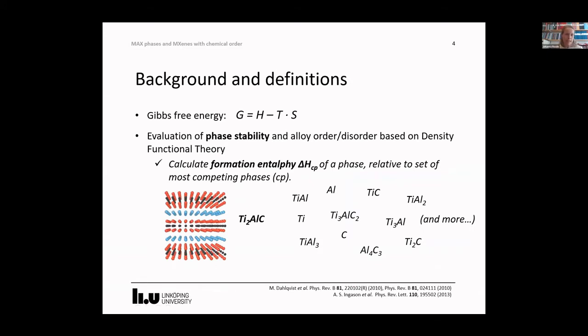So if we take titanium aluminum carbide as an example here, as I said, it contains 3 different elements, and out of those we can form several different phases: single elements, binaries, and ternaries. And if we calculate the energy for titanium aluminum carbide and compare that to the energy of these phases or a linear combination of these phases, then we find that a linear combination of these two is actually a set of most competing phases, though they are not more stable than this one. So this one has a formation enthalpy of minus 27 meV per atom, meaning that it is predicted to be stable.